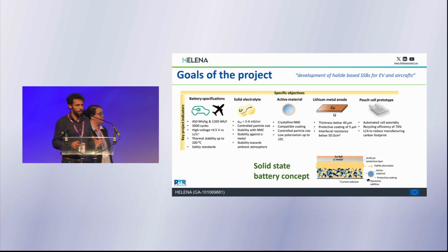And so there is activity around these active materials, with development of coatings to ensure higher rate capabilities. And there is also activity on lithium metal. Lithium metal is a key component for all the projects that are going to be presented here. It's very important to develop solutions for lithium metal, because as we push forward the energy density of the batteries, so does the reactivity of the materials. Halides can be very reactive towards lithium metal. This is why we need to develop coating solutions to prevent degradation and to ensure performance in the long term.